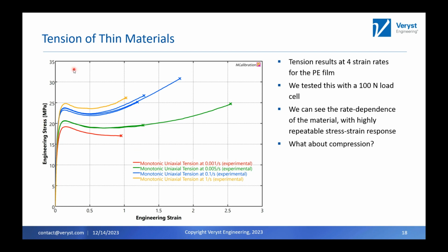But I love these curves. They're beautiful. They're so smooth. If I showed you this, you wouldn't expect that I was testing 100 micron film. You would think that I'm testing a normal material, 3 millimeters thick. So again, testing thin is not an issue. We've also done these at high rates, which we can do on our drop tower. We don't have any data I can share, unfortunately, but we've got the material and the capabilities to test these at higher rates as well.